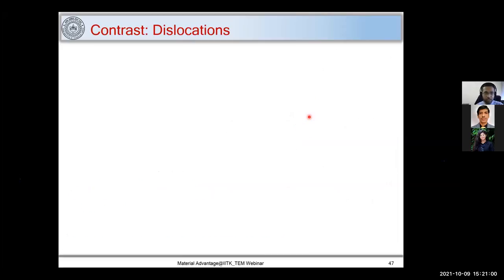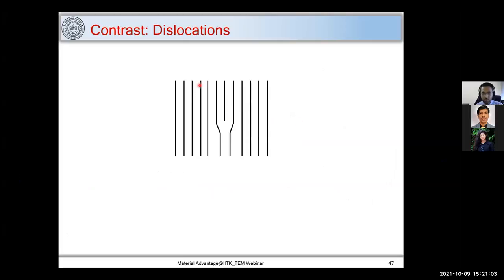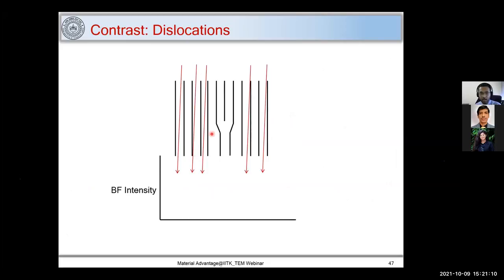Now, in dislocations, the contrast comes, so let's understand how. Here we have an edge dislocation, and here are our incident rays. Let's plot how intensity varies with respect to this dislocation's interaction with the electron beam. I consider I naught to be the initial intensity, and IT is the transmitted intensity. When the electron interacts at these planes, near the core of these planes Bragg's condition is satisfied. So these planes will undergo diffraction, and I call this intensity ID, the diffracted intensity, and I can write I naught as IT plus ID.